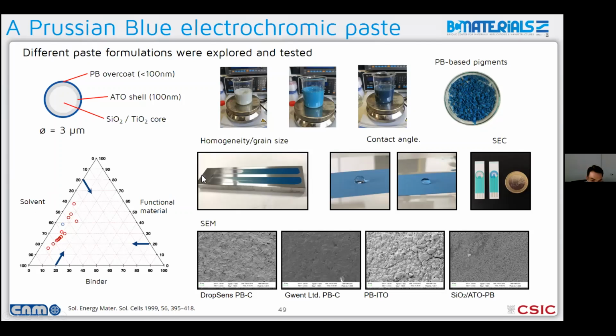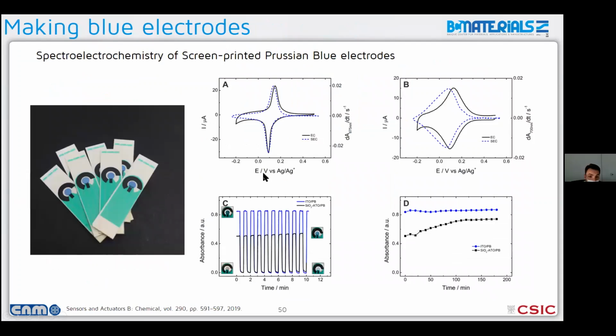So we played with different solvents, different binder materials. We looked at how these would behave on a screen printing process. We checked contact angles, because initially we thought that if it was hydrophilic, it would be best, but then in the end, the Prussian blue is not really in contact with water. But you can see that you can play with the composition and achieve different behaviors. And then we did some spectroelectrochemistry to characterize the inks. So we have printable Prussian blue, which is very nice, on different types of substrates.